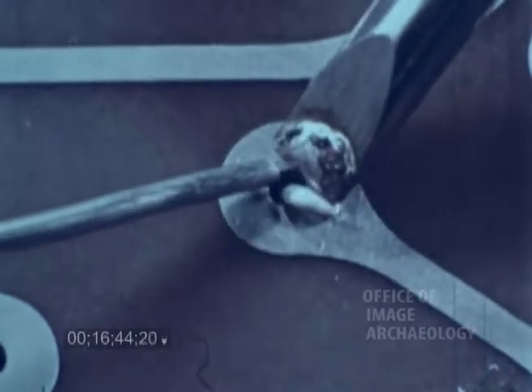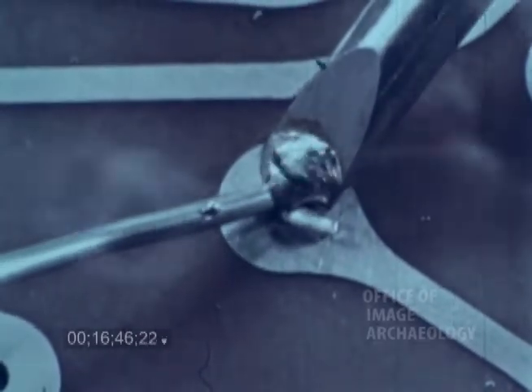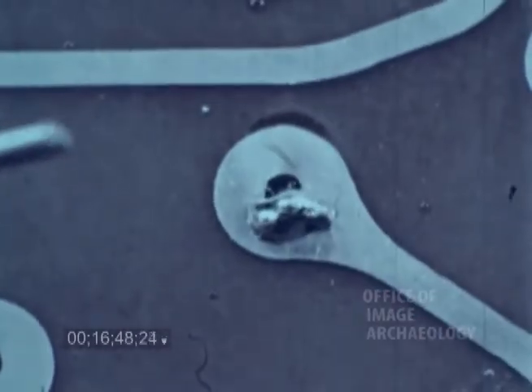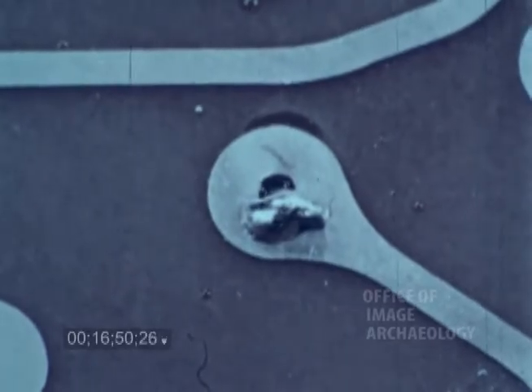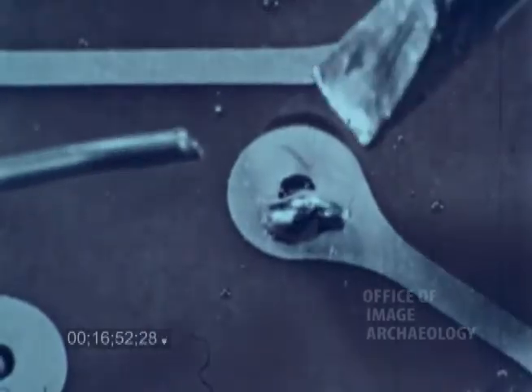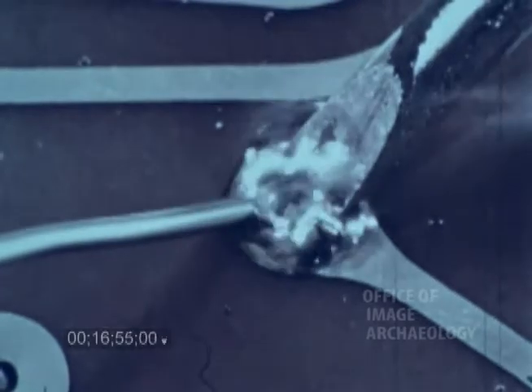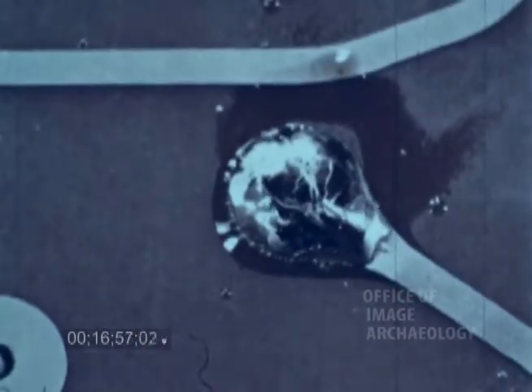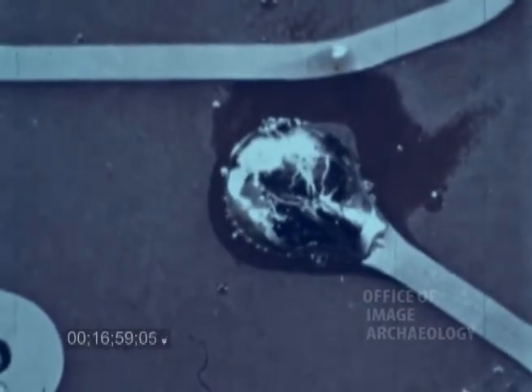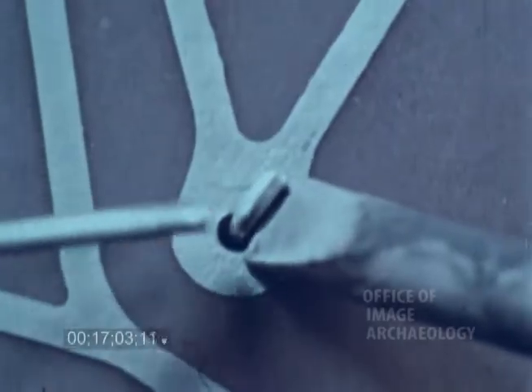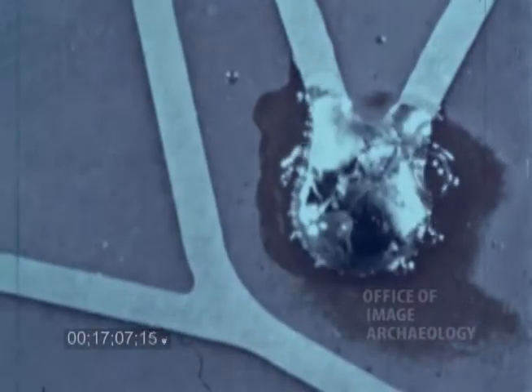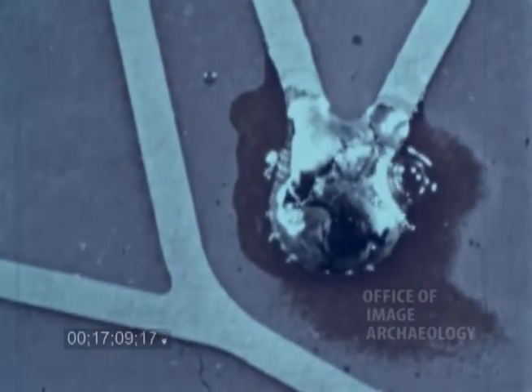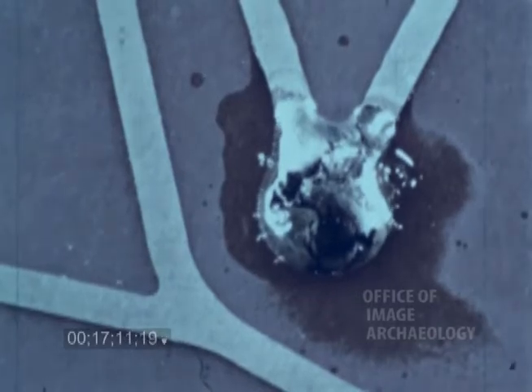Never apply the solder to the iron in hopes that it will run off onto the connection. The flux is burned away and there is no wetting action. Heat the connection, then apply the solder. Allow it to cool without disturbance, and you will have produced a reliable connection. Be careful not to jar the connection while it's cooling. This could produce a fractured or cold joint.